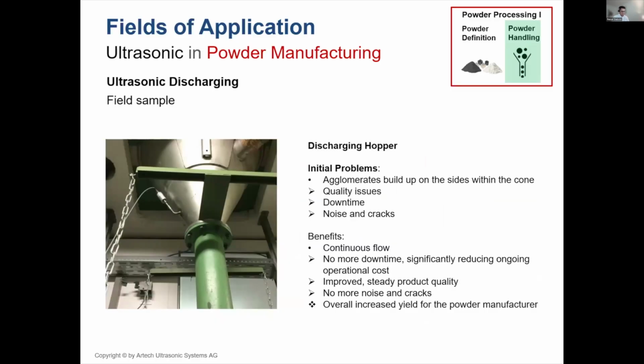Let's have a look at one of the field samples. So this is a discharging hopper, discharging aluminum oxide powder. The problem here was that agglomerates build up on the inner walls of the cone. That caused quality issues for the end user because the agglomerates were falling down the pipe like snowballs into the final product. This was not desired by the customer.